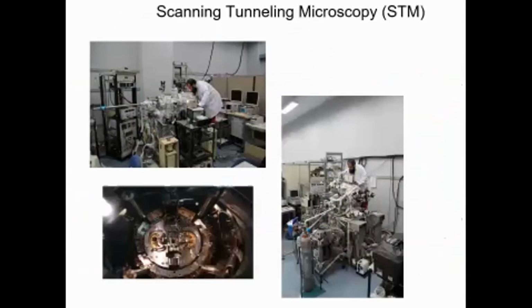We also use a scanning tunneling microscope. It's not an easy technique to use, and it's a bit challenging because you are getting the tip very close to the sample. It's just a gap of 1 nanometer. And with any contamination, any impurities, any kind of damage, you will lose the signal. In the scanning tunneling microscope, we measure the tunneling current. These are electrons jumping from the tip to the sample, by applying a bias voltage to the sample and trying to measure.